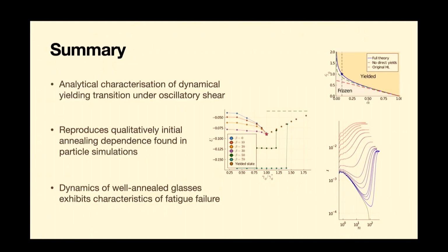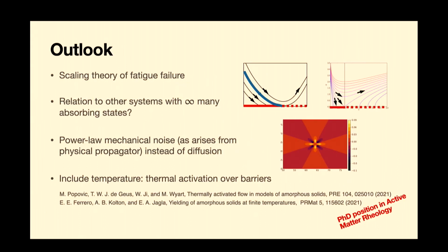We get from this model not just the steady state phase diagram, but also the history dependence, the interaction of the two kinds of non-equilibrium. It looks very much like what people see in experiments and in MD simulations. And then we find in the dynamics this interesting characteristic behavior that looks like fatigue failure, where the material looks like it's going to more or less survive in an elastic state until it yields at the last minute.